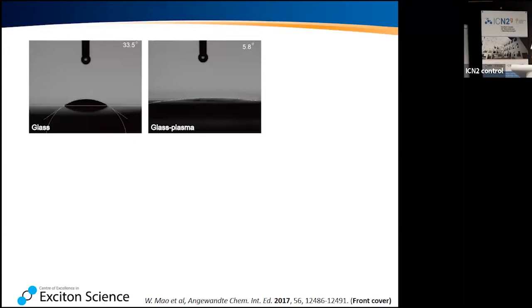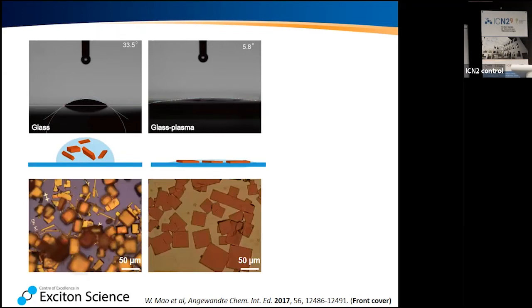One more thing that Wen-Chin developed was he realized that if he pre-treats the surface onto which he drops that precursor solution, it makes a huge difference. And the reason simply here is just geometric limitation of your film thickness. So your film becomes much, much thinner if you plasma clean your surface and the contact angle is very, very small. And that means that if we have a big droplet, we get almost cube-like structures. If we have the very, very thin film, we get these beautiful platelets. Shown here, these all look quite similar in terms of their height. And here, if we don't do that, we get all sorts of things in our structure.